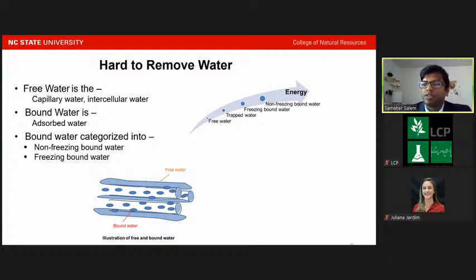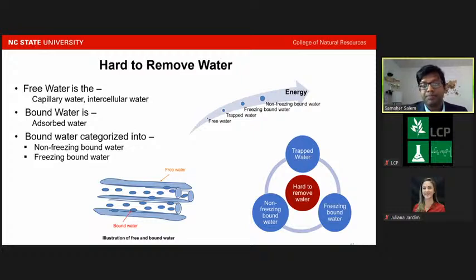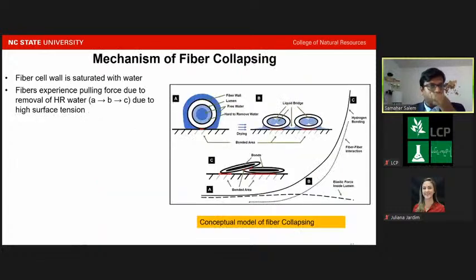Since the hydrogen bond is increased relatively by two orders of magnitude compared to the bulk water, and the entropy of the adsorbed water molecule in the sorption site decreases, which in turn increases the stability of the bound water and requires higher energy for drying to overcome capillary forces. Thus, bound water along with the trapped water forms hard to remove water. Now, this is a mechanism of fiber collapsing.